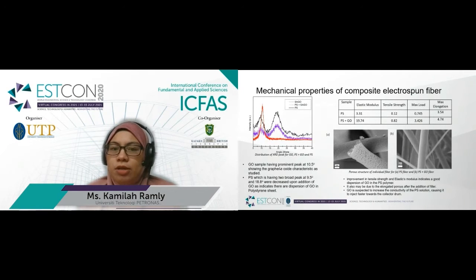From the XRD result, the GO sample has a prominent peak at 10.5 degrees, showing the graphene oxide characteristic. PS, which has two broad peaks at 9.5 and 18.8, decreases upon addition of GO, indicating there is dispersion of GO in the polystyrene sheet. The improvement in tensile strength and elastic modulus, as shown in Table 1, indicates a good dispersion of GO in